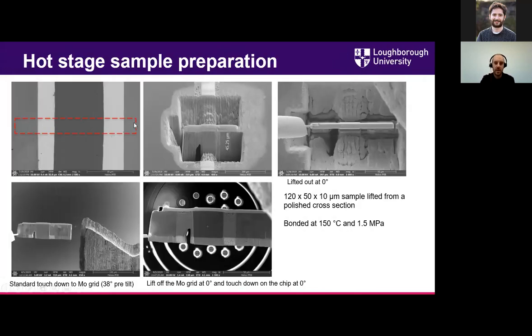So we took a sample from one of these self-propagating exothermic reaction or nanofoil bonded samples. We took a TEM lamella out of that, and you can see this is where the PFIB really comes in handy. So the lamella size was 120 microns long, 50 microns deep, and 10 microns thick. So this was relatively easy to cut in the PFIB, but if we'd been using a gallium FIB system, this would have taken a really, really long time and been quite challenging. But having access to those higher currents allows you to take these large bulk samples.